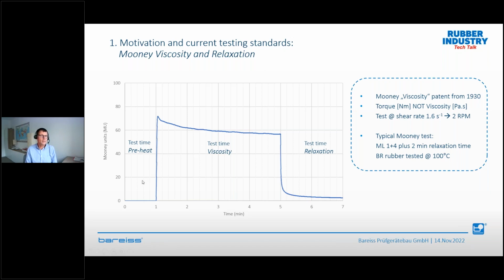We have the preheat time, normally 1 minute. We have a test time, which is called the viscosity test. And sometimes people are using additional, for example, 2 minutes after testing, stopping the rotor. We are doing a relaxation test. So this is a typical test which is used in the rubber industry, and it's called the ML1+4, which means Mooney large rotor, 1 minute preheat time and 4 minute test time. This is a standard test which is well known in rubber industry.